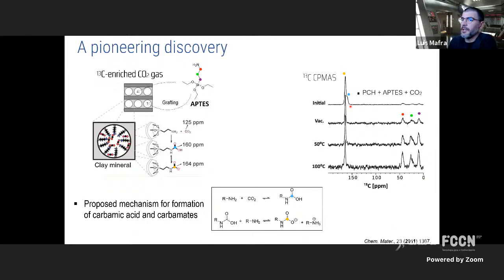You really need to heat it a lot. Even heating, it doesn't go away. You need to put water inside, okay, to reverse the reaction. And this is all under dry conditions, okay? So we immediately thought that it was carbamic acid. And this was the first indication of the existence of carbamic acid that could explain many other pathways to the formation of adsorbed species.